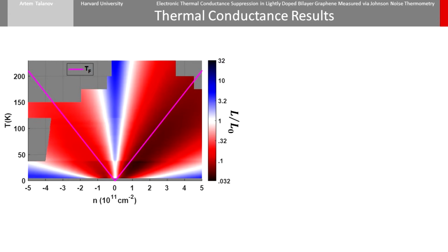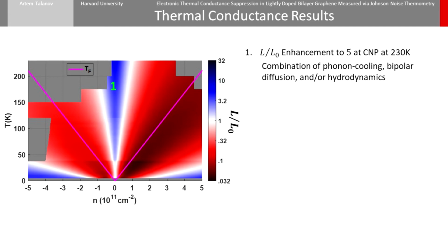We can identify 3 distinct regions where the Wiedemann-Franz law is violated. The first region shows an enhancement by a factor of 5 at charge neutrality and high temperature. This is somewhat similar to what is seen in monolayer graphene, except here there is no upper temperature cutoff. It's thus hard to attribute this increase to hydrodynamics. The best we can say is it is likely some combination of cooling to the phonon bath, bipolar diffusion, and hydrodynamics, but we don't know in what ratios.